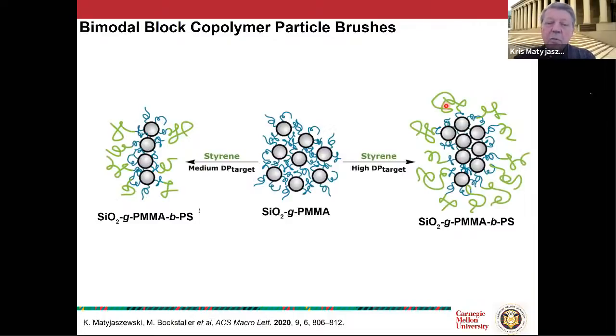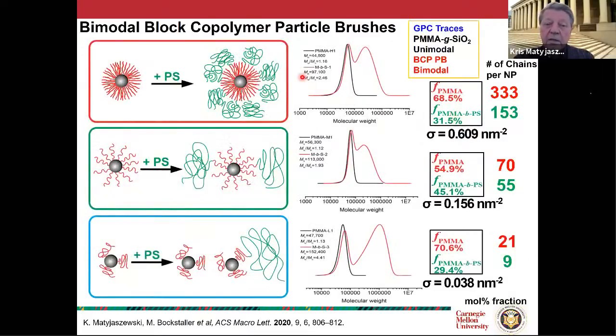These can be extended to block copolymers. So for block copolymers, we can start with silica with PMMA, and then they can be extended with the corresponding polystyrene, either short or longer ones. And again, morphology would be pretty different depending on the structure. We can have more polystyrene and dense PMMA grafting, or sparse PMMA and even more sparse polystyrene. So you have some unreacted PMMA nanoparticles.